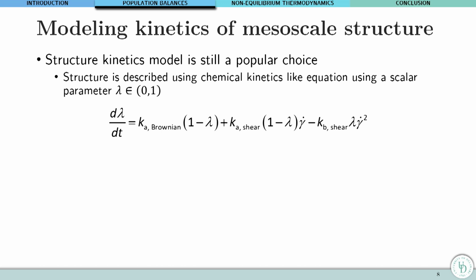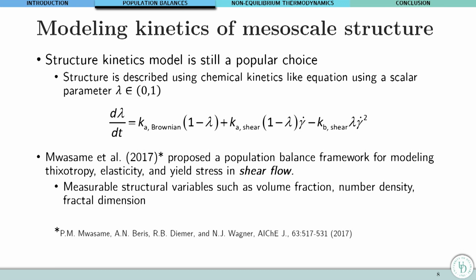So coupling this type of kinetic expression with expressions for the stress that come typically from either the theory of plasticity or from viscoelasticity, many workers, and also ourselves with our former student Mwasami, came up with theories that were pretty good in predicting the behavior of aggregating systems fairly accurately, but with a problem. The problem was that the theory contained too many parameters and was primarily applicable only for shear flows.